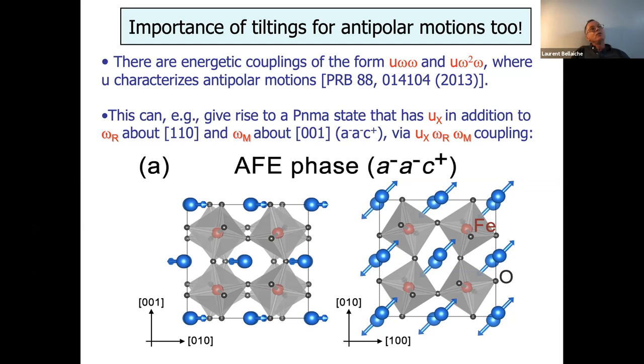So basically, if I look at the one, zero plane, all the cations move along 110, but if I go to the zero plane above it, now the cations are moving along the -1, -1, 0 direction. So opposite, it's a nice antipolar motion.